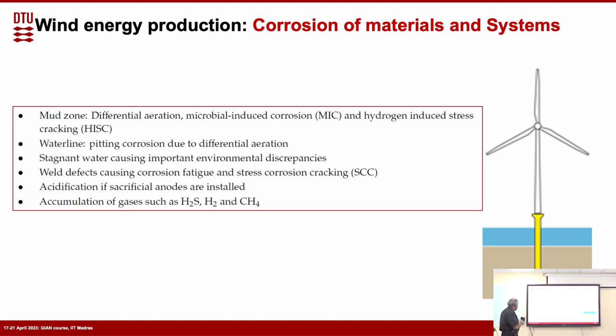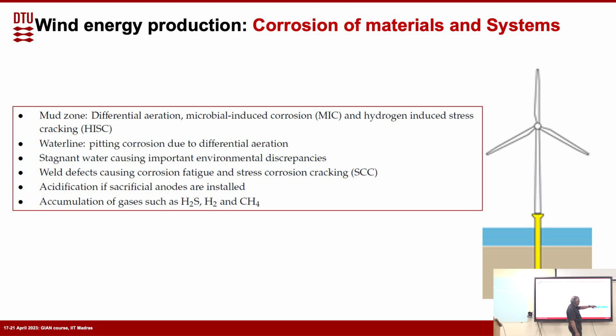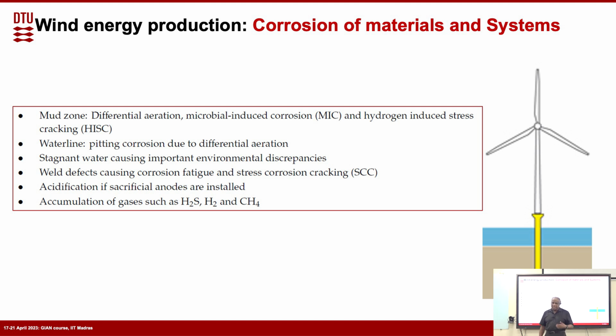So waterline corrosion is pitting due to the differential aeration in this area. Again, they say that it's pitting, but that depends upon which material you are looking at and things like that. And of course, all these are probably heavily painted. Since it is a painted structure, the paint is delaminating, and that way you have the corrosion problem. That's the reason that very seldom will you see really uniform corrosion. It's paint delamination and corrosion happening underneath.